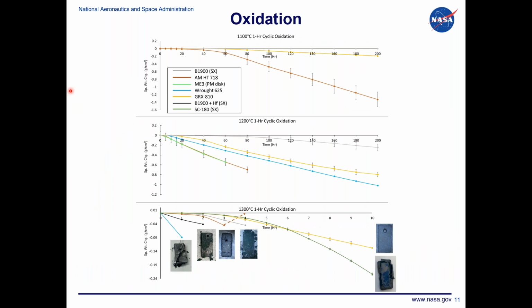We've done some new oxidation studies, looking at cyclic oxidation at 1100 C 1 hour cycles, 1200 C 1 hour cycles, and 1300 C 1 hour cycles. And I'll be honest, we had a multitude of other alloys that we wanted to compare it with, and I've had some colleagues ask, why did you use these alloys? A lot of the reason is we had them on hand at the time. But we wanted to make sure we were definitely comparing it to 718 and 625. We also wanted to add some alumina forming superalloys like single crystals, B1900 and SC180. When it comes to oxidation, alumina is really your gold standard in terms of protection. With GRX-810, there's not enough aluminum in it to form an alumina layer, so we're relying on the chromia, but also the nanoscale yttria, for our oxidation protection.